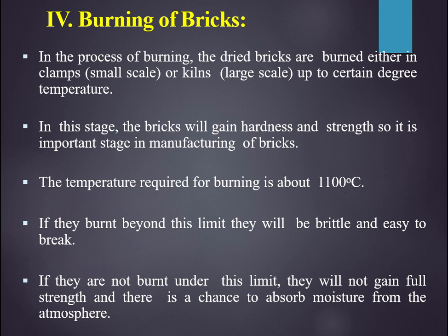Before, as told, whatever strength and durability we require for our brick will all be obtained in the burning step itself. The temperature will be around 1100 degrees centigrade, and if it crosses 1100 degrees centigrade, your brick may become very brittle in nature, something like a biscuit. So if you break it, it breaks very easily. That's called the brittle nature.